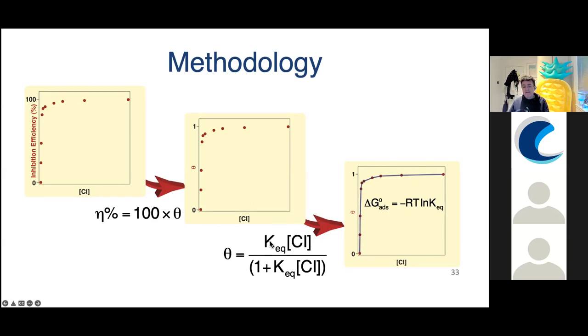Then the next stage is to use an adsorption isotherm to model this uptake, the coverage of the molecule. The one I'm showing here is the Langmuir isotherm, where theta is related to the concentration of inhibitor in bulk solution, Ci, multiplied by the equilibrium constant for that reaction, all over one plus a similar term. And you get this behavior here. Then you fit these data. You know the corrosion inhibitor concentration, you know theta, so you can extract the equilibrium constant. Then you can use this standard equation to get the standard Gibbs energy of adsorption. And that's what's done. However,